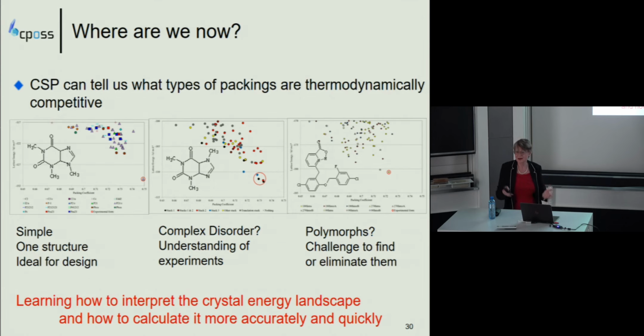So caffeine, the low temperature form, is statically disordered. The high temperature form is nice and symmetrical because the molecules are whizzing around in the plane, and those are just some of the structures that contribute to the disordered structures. It helps you interpret the experiment. The usual position is that you're predicting polymorphs with a challenge to either find them experimentally or eliminate them as being of no concern or interest.